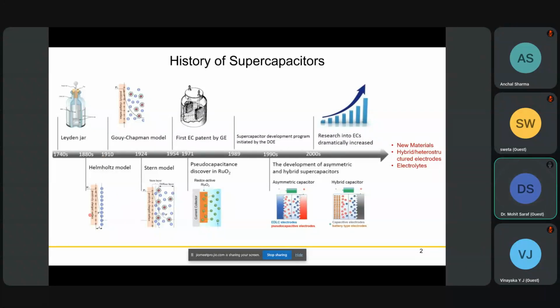But it does not take into account the diffusion of ions, or basically the thermal motion of ions. So in 1910, the Gouy-Chapman model was proposed, where they take into account the thermal motion and diffusion of ions, and basically the charge distribution happens as you go further from the electrode surface, according to Boltzmann statistics. But again, this model was valid for low ionic concentration of electrolyte. So it was further improved by the Stern model, where we divide the whole system into three layers: the inner Helmholtz plane, the outer Helmholtz plane, and then the diffuse layer.